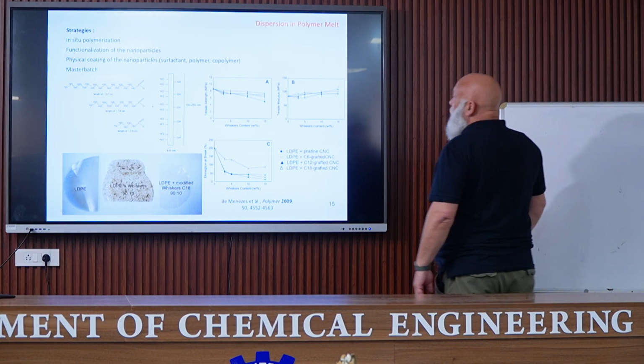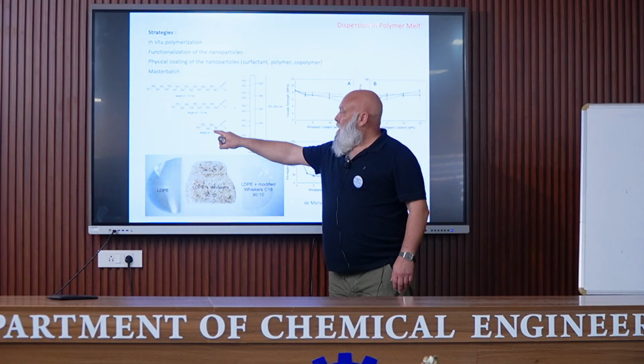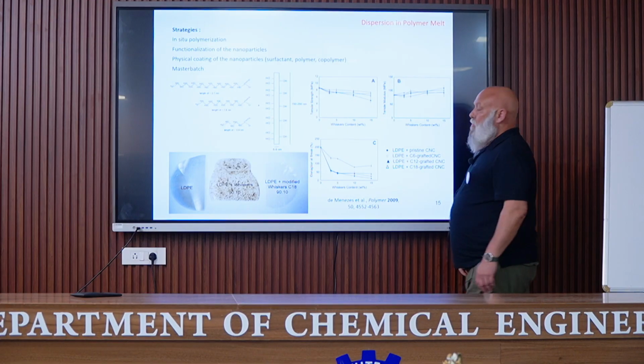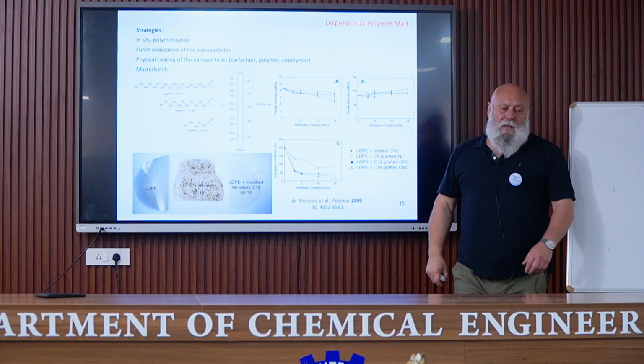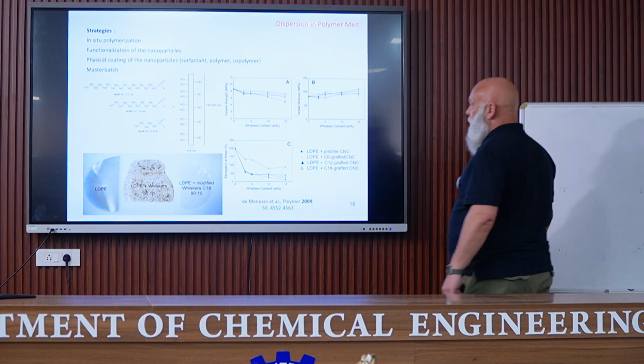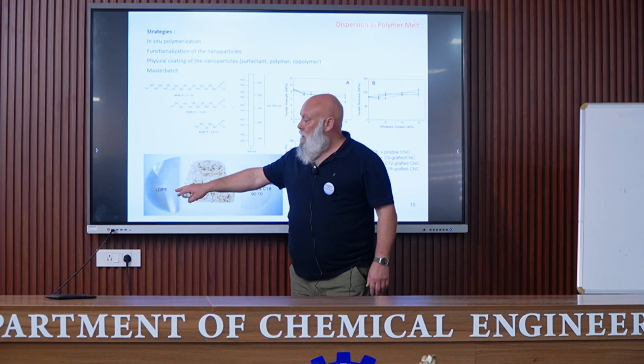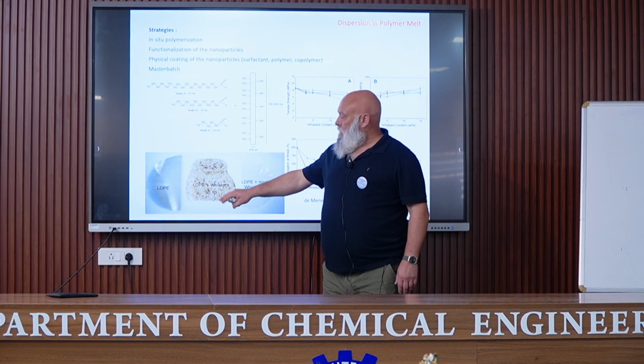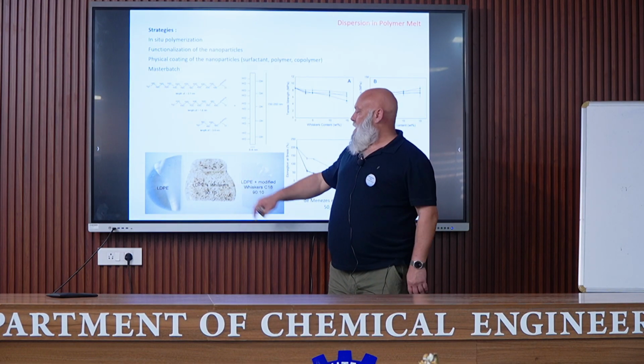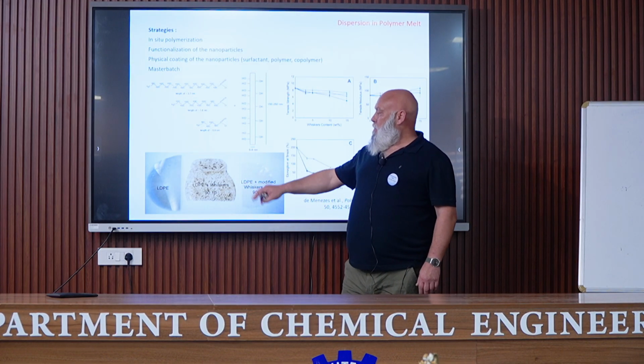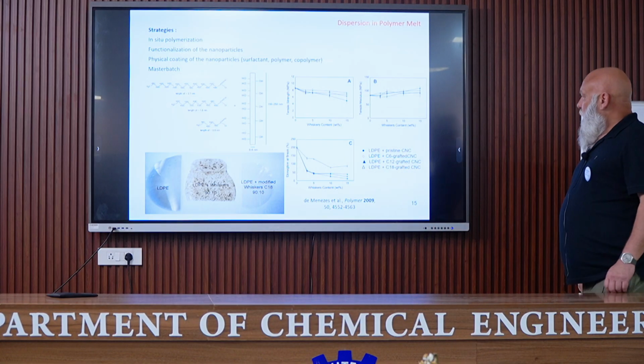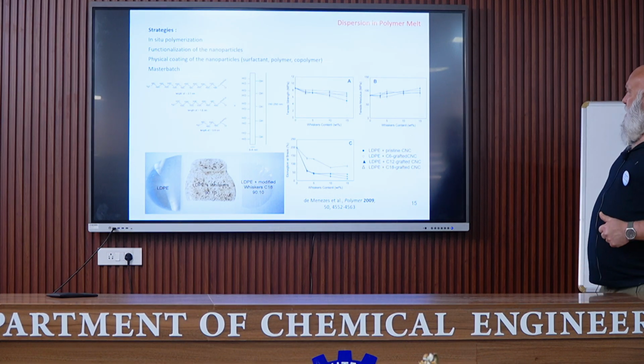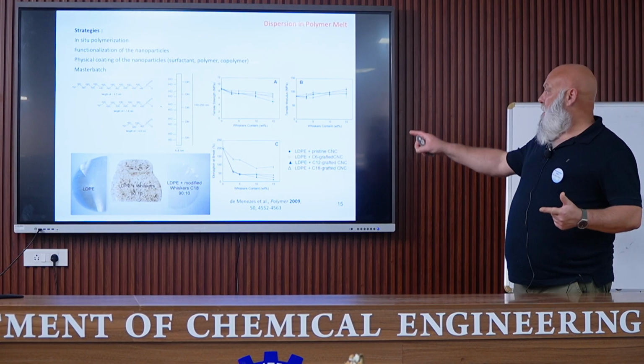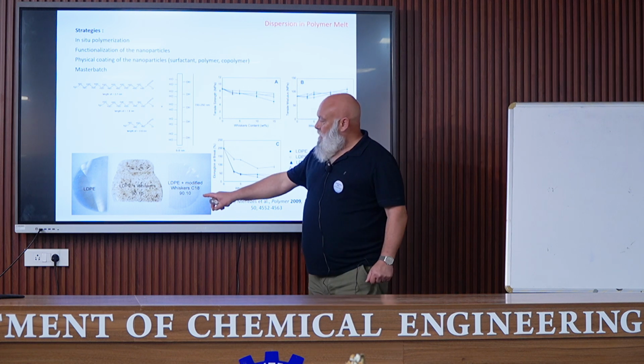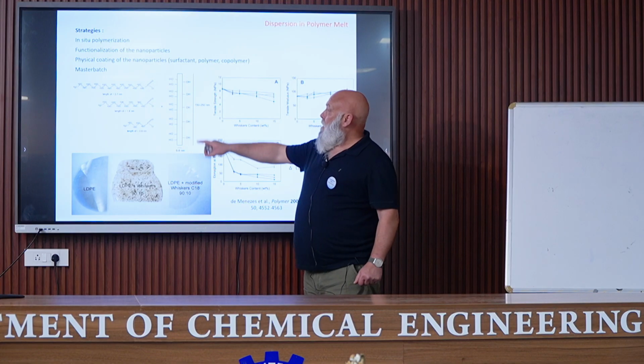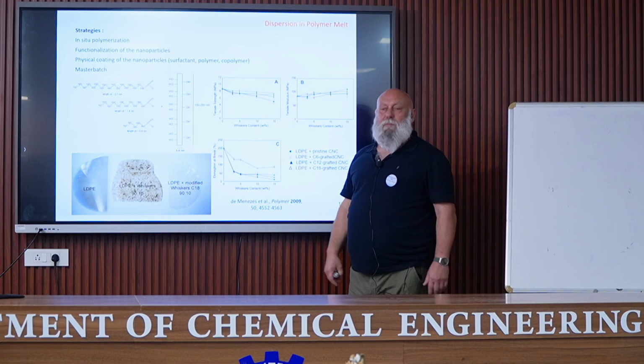I will show you an example in which cellulose nanocrystals have been grafted with aliphatic chains with different lengths. So it was an esterification process, and these nanoparticles have been extruded with low-density polyethylene. So you can see the aspect of the low-density polyethylene here, and this is this polymer that was extruded with 10% of whiskers or nanocrystals, which were not modified, and you can see several brown dots, and so this reveals, of course, some aggregation of the nanoparticles, but also some thermal degradation, because of the change in the color. And here you have the same polymer that was extruded with 10% of modified nanocrystals using the longer chain, and you can see that the aspect is completely different.